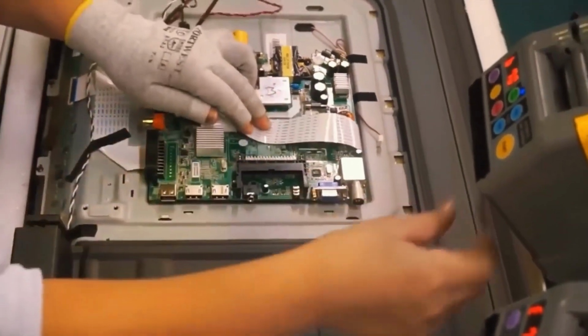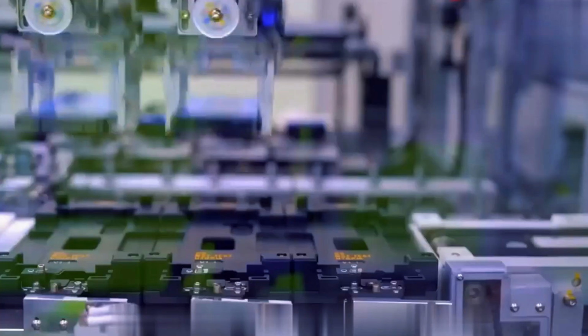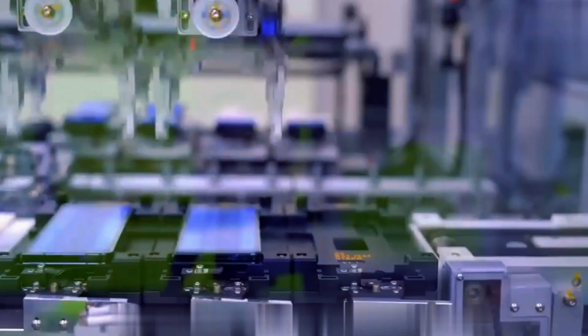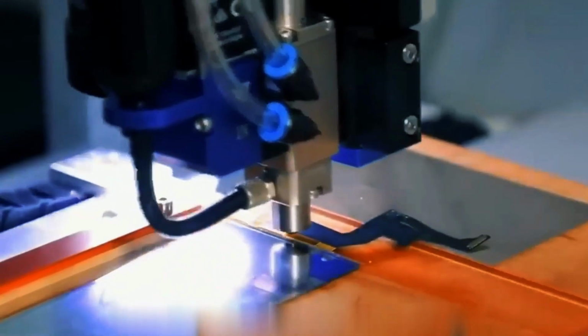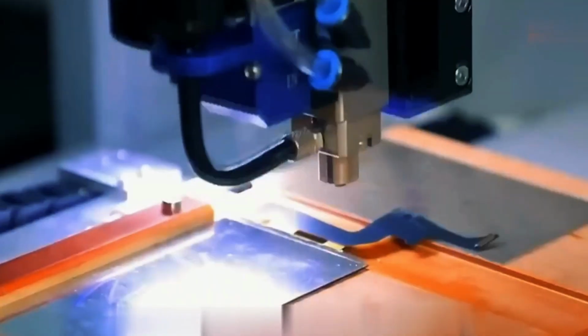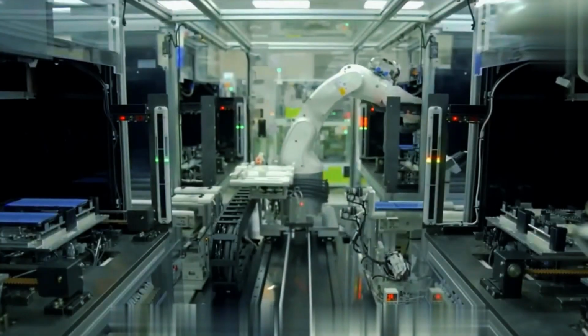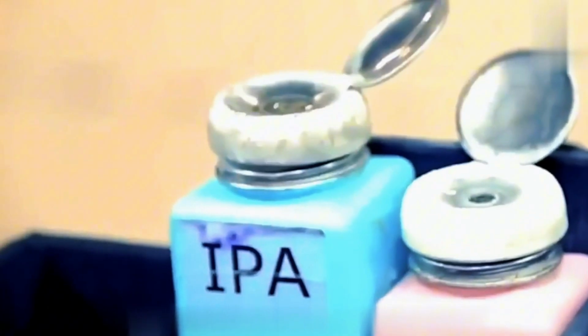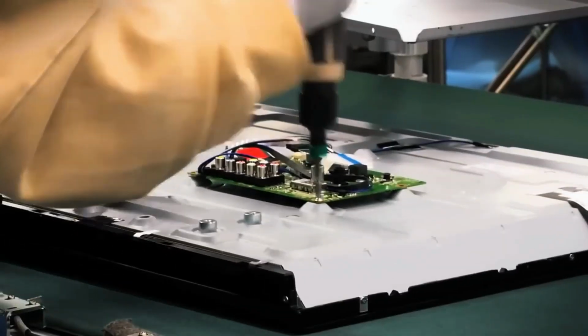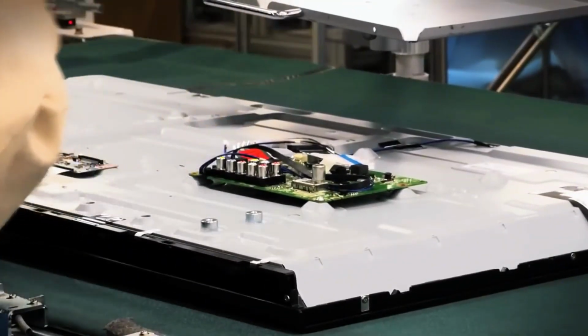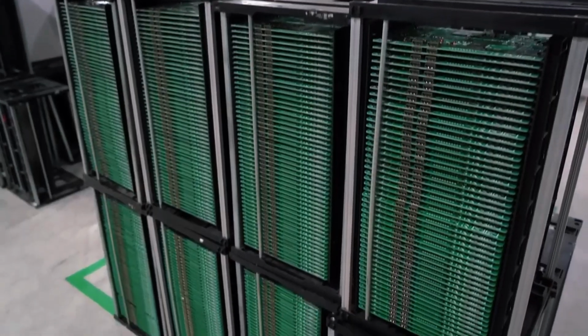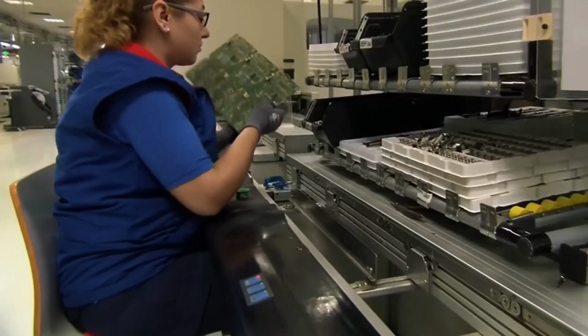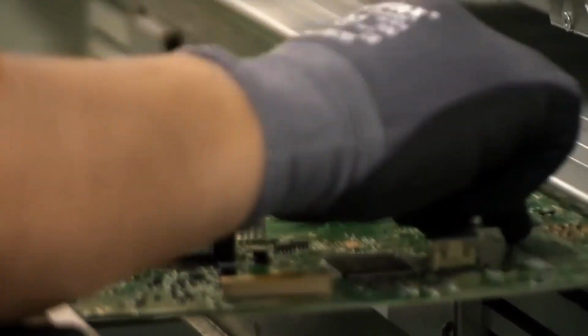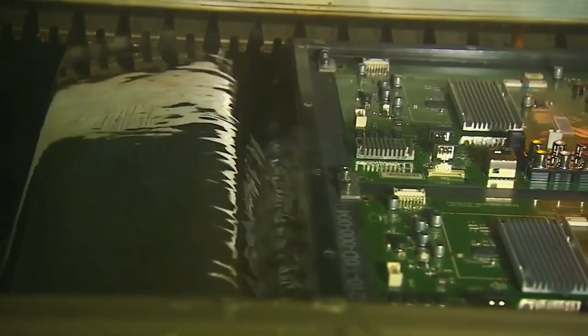For smartphones, especially flexible displays like OLED, inkjet printing is often used, depositing minuscule drops of soluble materials, much like an office printer but on a nanometric scale. This reduces material waste from 90% down to 10% and is more scalable for large panels such as QD-OLED televisions. In TVs, the challenge is greater due to the size. Substrates, which can be up to 2.5 meters wide, require massive masks and perfect alignment to avoid defective pixels.